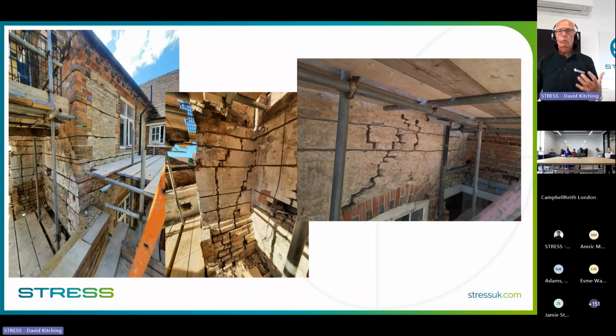So here we go. So we've got all that wall chasing, and the beauty of the wall chasing is that you can remove very neatly the mortar in the joints. But you'll see here we've got stonework, and the joint cannot be in a straight line. Remember us talking about hiding joints. If we cut that straight, which would be the easiest thing for us to do, it would just nip off bits of stonework and you'd end up with a lovely straight line. Once that's repointed, it will stand out like a straight line as opposed to all the slightly irregular stonework around it. So in fact, we take out the mortar along the line, the uneven bed joint line. Pop the bar in, because the bar will nicely undulate around that. Pop the grout in, grout it well into position, and when it's repointed, you won't be able to see where that's been.